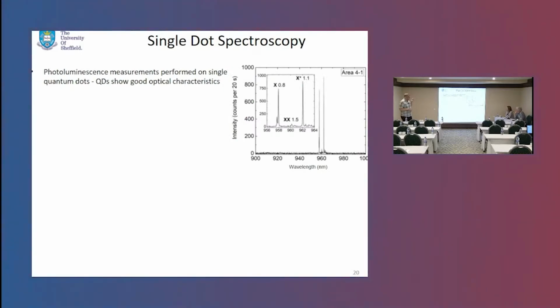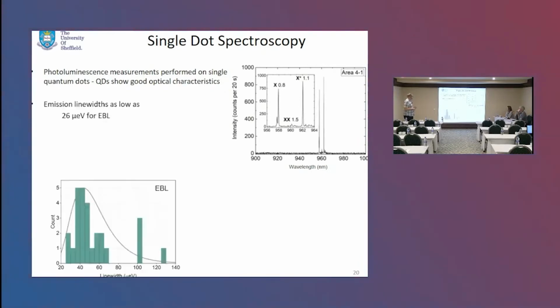So if we look at those dots now in the third technique, which is to measure each dot individually, measuring its luminescence, we can actually then start to measure the line width and see, do we have sharp lines? Do we have exciton, biexciton and so on? And they do show good optical properties.